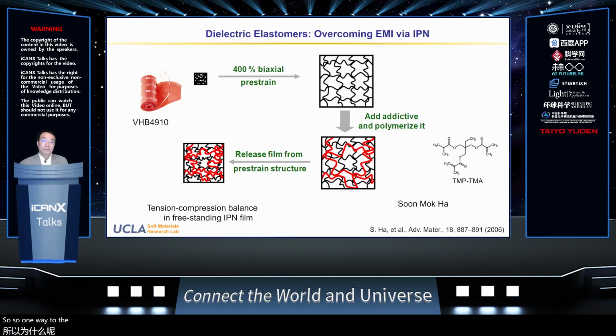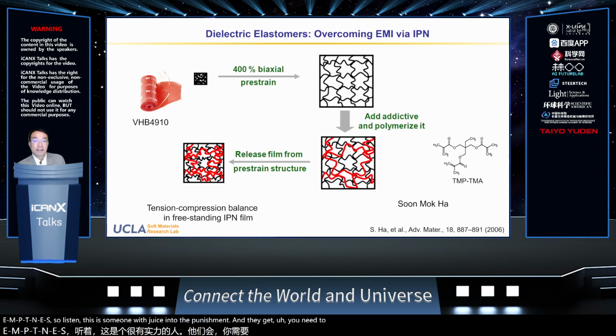So one way to overcome this issue, which we introduce here, is making an interpenetrating polymer network dielectric elastomer, or the IPN DE. The way to prepare this film is starting with the VHB film, pre-stretch it biaxially by 400% or as much as you can pre-stretch the film. Then you spray difunctional acrylates, or trifunctional, like the one shown here, TMPTA. This compound will diffuse into the polymer, and then it gets UV cured, and then you relax the film.